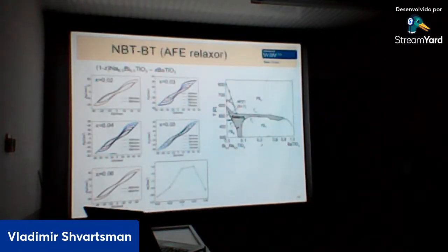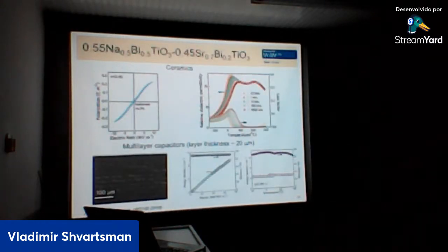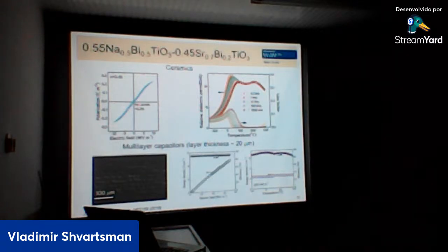And finally, I was speaking about relaxors, and I was speaking about antiferroelectrics, and people try to combine these two concepts. They try to find an antiferroelectric relaxor material which will combine advantages of both antiferroelectric and relaxor materials. So slim double hysteresis loops, for example, in this system of sodium bismuth titanate, barium titanate, or a more complex system when we add to these materials also another component, strontium bismuth titanate. So you see, in this material we have a pretty ideal case. We have a double hysteresis loop, but this double hysteresis loop is very slim, so the area of hysteresis is very small. The efficiency of this material stays about 90%, about 80%, with energy density